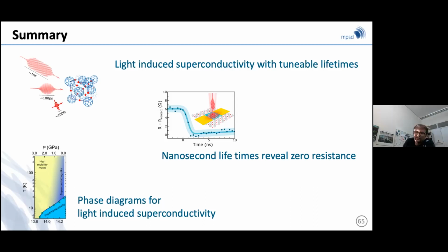Okay, but you don't see any change in the spectrum or the spectral shape of the response function or something? I mean, the Drude-Lorentz fit, when we try to extract sigma 0, is only used for that purpose and at frequencies lower than the gap. Right, there sigma 1 is 0 and sigma 2 diverges as 1 over omega. So in that sense, it is by construction a perfect Drude-Lorentz fit at frequencies higher than the scattering rate. We have selectively chosen a spectral region where Drude-Lorentz works by construction. But this is only for the purposes of trying to predict sigma 0, just to have one quantity to be looked at. Yeah. Okay, thank you.